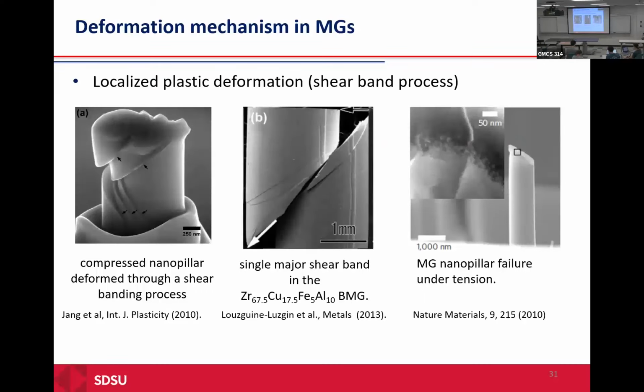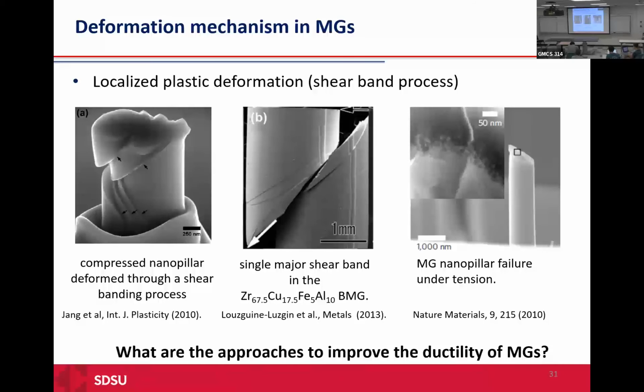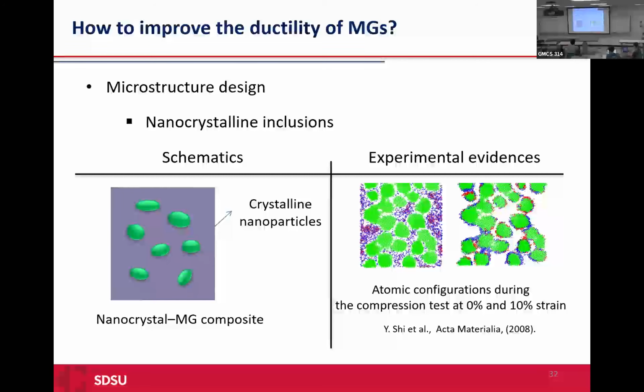But like other materials, when they have very good properties, usually they have some drawback as well. And what is the Achilles heel of this type of material? They usually suffer from very dominant shear band formation that makes them really brittle. These are some of the experiments that show the formation of shear bands in this type of material. Then we want to see what the approaches are to improve the ductility of this metallic glass and to avoid this localized plastic deformation or shear band formation.